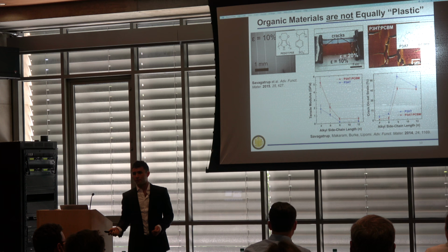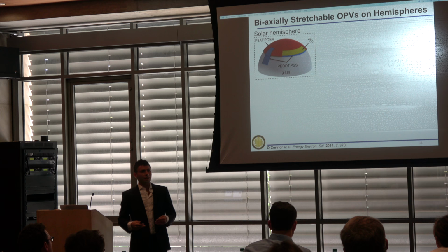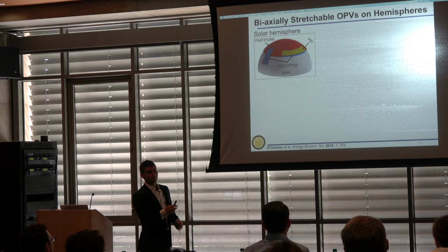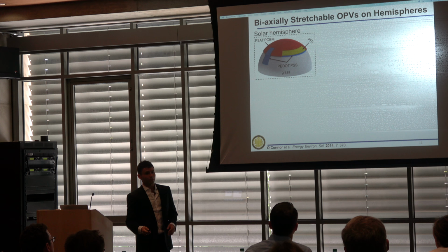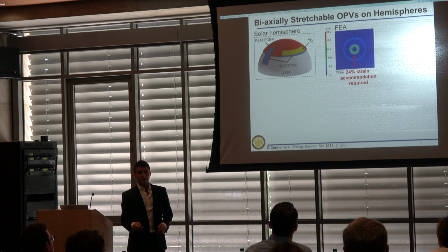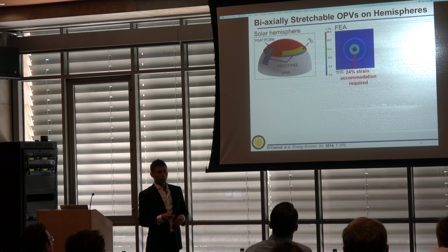So we wanted to demonstrate how critical this was in device fabrication. So I designed a biaxially stretchable OPV that we transfer printed on the surface of this glass hemisphere. And we tried this experiment with C6 and C8. We used finite element analysis that predicted the device would need to accommodate 24% strain in order to maintain uninterrupted function.